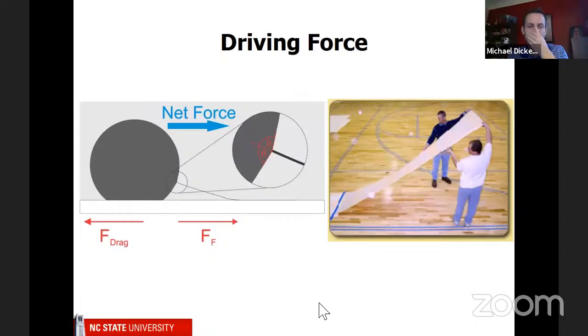And so what we think is happening is, if you imagine that this is the liquid metal and this black thing is the silver film that's resting on this surface. So it's resting here and then it gets pulled up. Well, it ends up being a force that's pulling it along. And the best analogy I can think of is to imagine the forces. So these guys are pulling a film off of a surface. They have to pull up, but they also have to pull over. So there's a force in two different directions. Well, it turns out that it's a little bit more complicated.